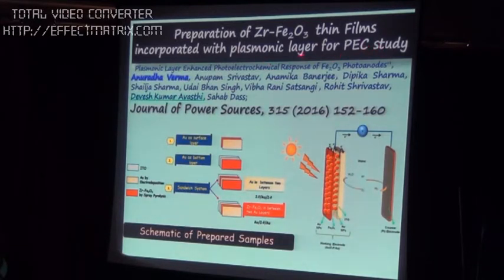We used plasmonic layers. That means we either put them at the top or at the bottom, or we sandwiched them. In either case we saw that there is an increase in hydrogen production. So that was a very interesting result. And then we see that a lot of groups in other countries are also trying this to increase hydrogen production. And hydrogen is a good form of energy which you can store.